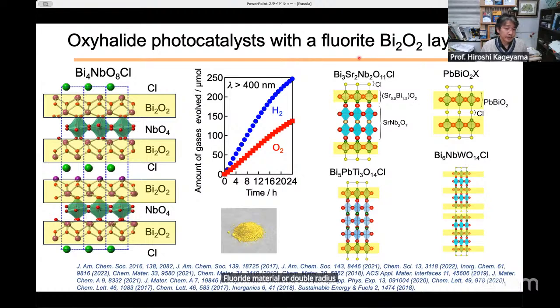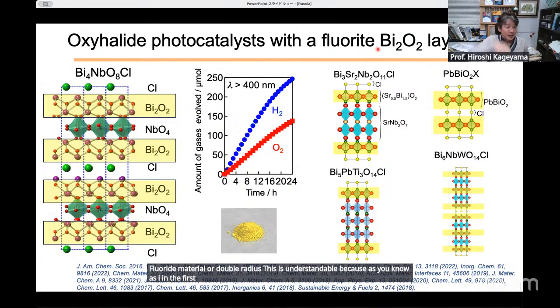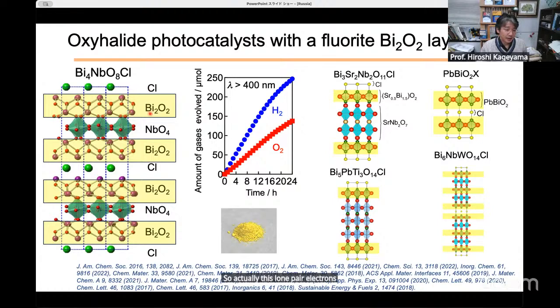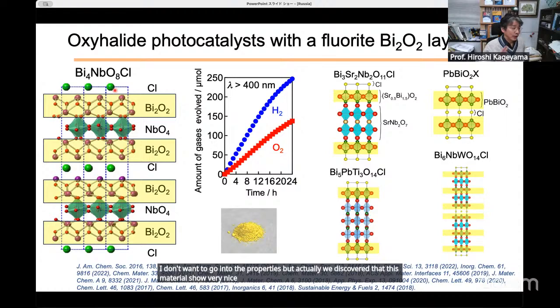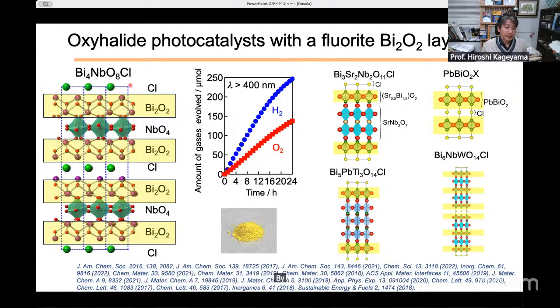Okay, so this is understandable because bismuth contains lone pair electrons. These lone pair electrons favor such double layer formations. And I don't want to go into the properties, but actually we discovered that this material shows very nice water splitting by visible light. And since this first paper in JACS about 9 years ago, we published a lot of papers based on these bismuth-based or lead-based oxyhalide materials. Okay, but commonly, these materials contain bismuth 2O2 layers.